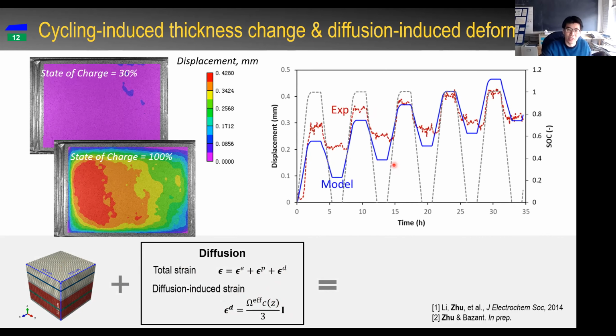So here are the predictions. The x-axis is time during charge discharge. This is one charge discharge. I showed 5 charges. So the gray dots are the SOC, state of charge, and the blue and the red curves are the displacement curves. So you can see during charge discharge, the thickness of the battery is changing, and the red is experimental, and the blue is our model prediction. So overall, the trend is good.